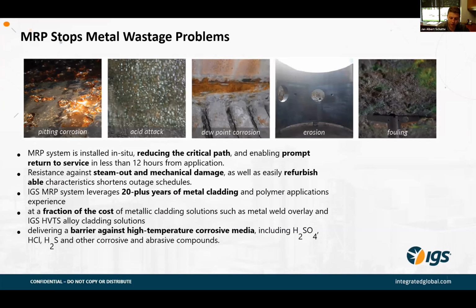So MRP is designed to be effective against all these wastage mechanisms in the pictures: pitting corrosion, acid attack, dew point corrosion, erosion, and also fouling. So it reduces the critical path time. It's practically no curing. So once the metal spray has been applied and the top coat has been applied, then within 12 hours of application, you have the equipment back.